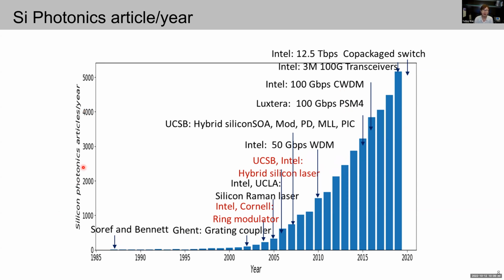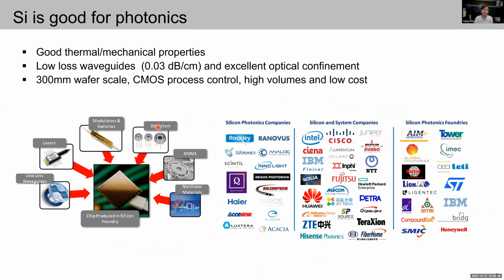This is the number of silicon photonics articles published per year as a function of the year, and you see an exponential growth in the number of articles published per year. So the impact of silicon photonics in academia is also growing rapidly. Nowadays, a variety of photonic devices can be put on silicon, including low-loss waveguides, modulators, switches, detectors, MEMS, and nonlinear materials. The foundry efforts across the entire world, especially in North America, Europe, and Asia, are quickly pushing the commercialization and wide deployment of silicon photonics, with many promised advantages like good thermal and mechanical properties, extremely low loss waveguides, as low as 0.03 dB per centimeter, excellent optical confinement, 300 millimeter wafer scale, high throughput processing, high volumes, and low cost.